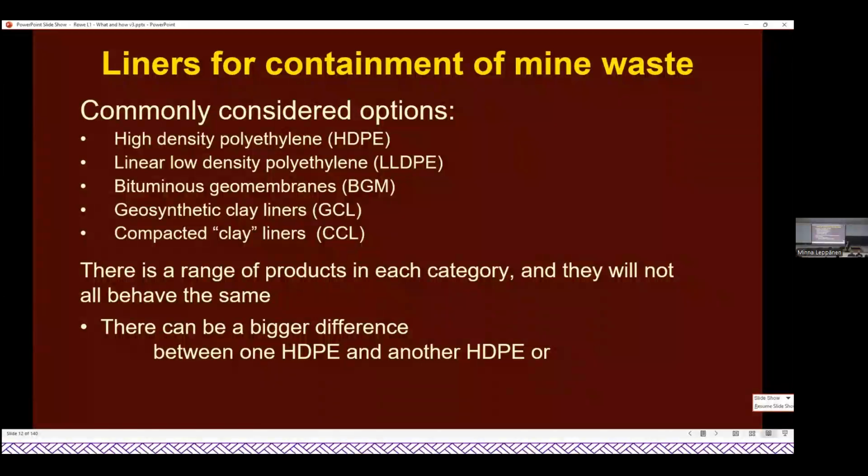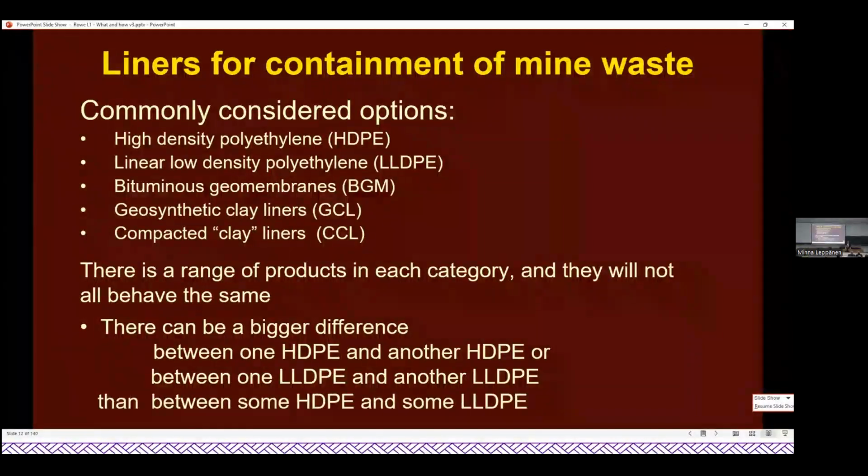So we have to recognize that when we're talking about HDPE, there can be as much difference between one HDPE product and another as there is between one linear low and another. And in fact, there can be more similarity between a good quality HDPE and a good quality LLDPE. So they say a cover doesn't tell you about the book. A name doesn't really tell you very much about the product.